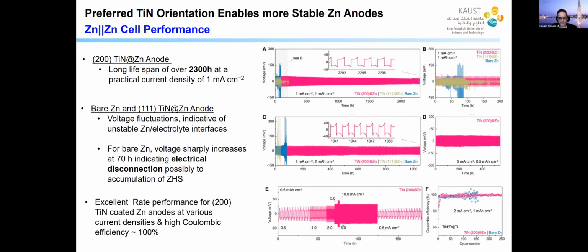Another thing, you see that you can do rate performance. Basically, you change the current density that you're passing through the cell, and you'll see that the titanium nitride continues to really perform well. And you see that the Coulombic efficiency of the titanium nitride, this is pink here, compared to the bare zinc, is substantially better. Actually, after a few cycles, nearly 100%.